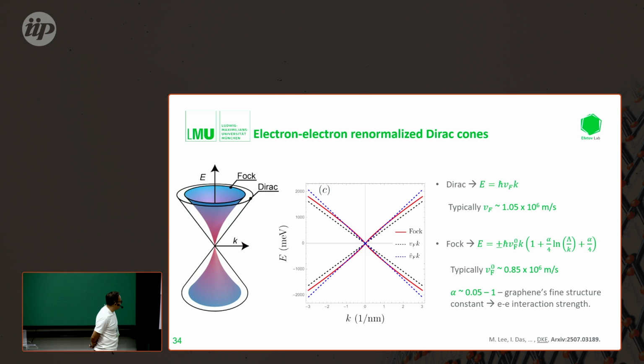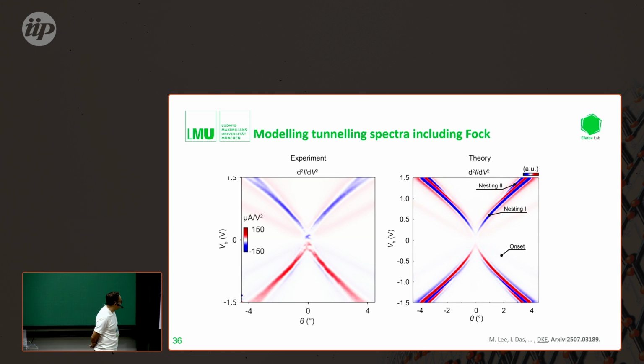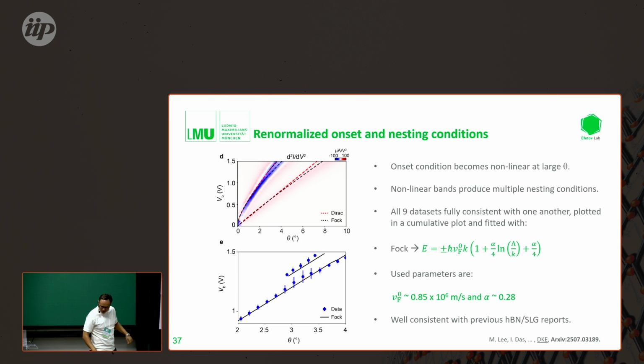Last but not least, what we were able to show is that not only the nesting conditions, but actually also the onset conditions that we obtain can resolve this effect, so that it's also becoming slightly nonlinear. So there's a second observable that points to this nonlinearity.